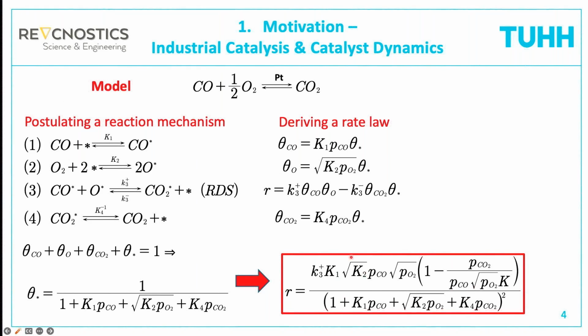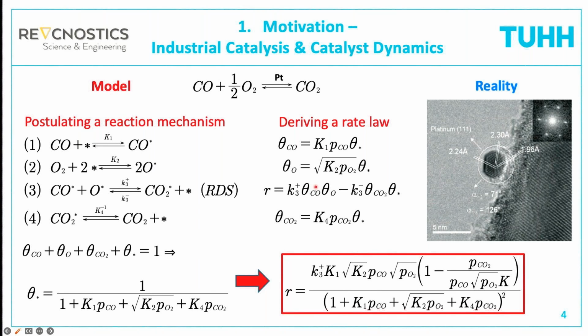And now we go to the lab and measure kinetic data, and then we fit the model to this data and determine the model parameters. So I'm explaining this to you so that you understand that we make a lot of very strong simplifications. We postulate the mechanism, we assume one type of site, we assume that the catalyst is static. And this is not very realistic, but this is the best we can do right now.